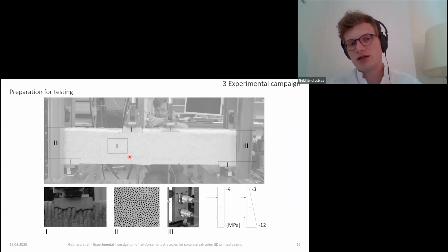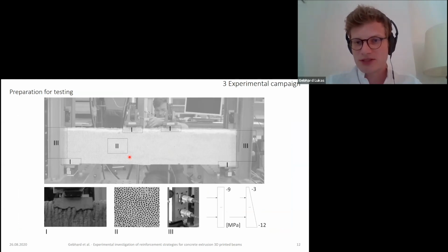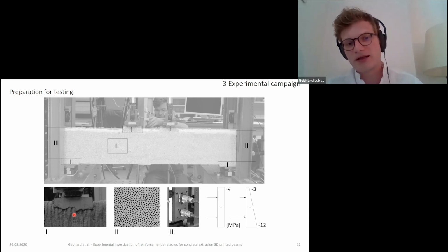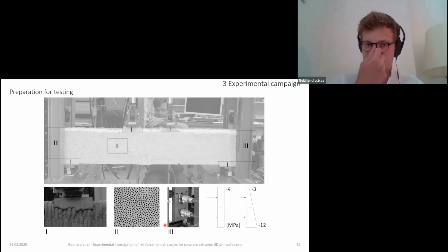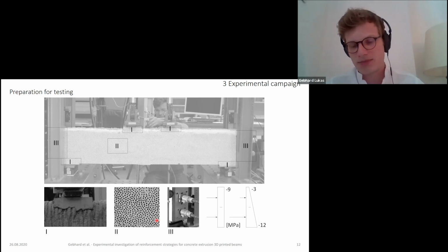Now, after printing, we had to do a few additional steps in order to be able to have good measurement. So one important part was the use of mortar beds, which you can see here in one, which had to be cast in all areas of load application due to the irregular surface of the 3D concrete printing. Additionally, we used digital image correlation to have a full field tracking of the displacements of the surface, where we applied a thin gypsum layer to have a smooth surface, then painted it white and put black speckles.